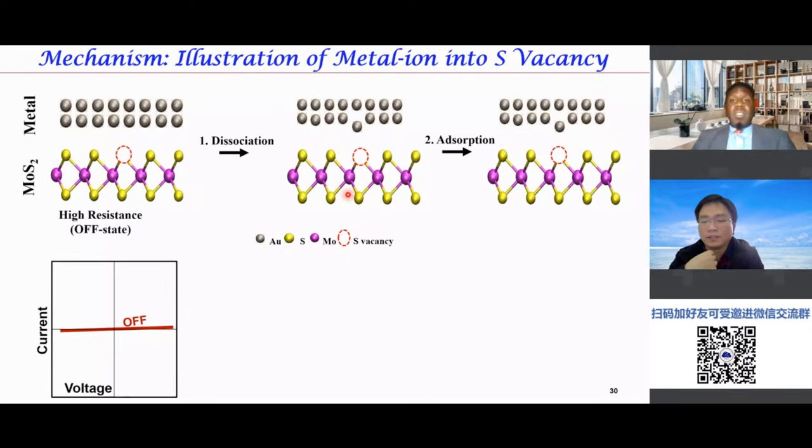There are also technical challenges, and one of them is how do you integrate this material on a flexible substrate? Right now, many of these 2D materials are not grown directly on a flexible substrate. They're grown on another substrate, like a metal substrate in the case of graphene, and then transferred onto the flexible substrate. That's a process issue that can introduce defects, dirt and contamination, and it's also an additional step. So there's ongoing research on whether you can grow them at high quality directly on flexible substrates and use them directly for those applications. There are other technical challenges, and I'll be able to discuss them offline.